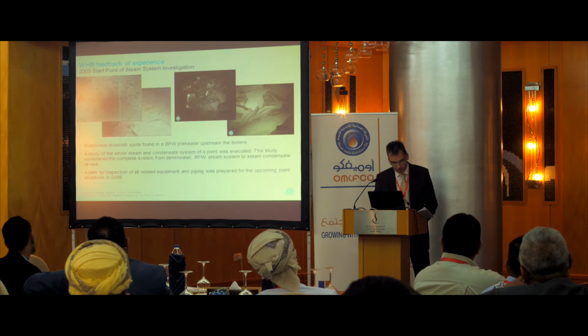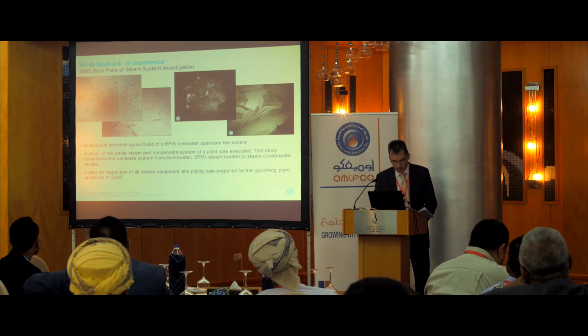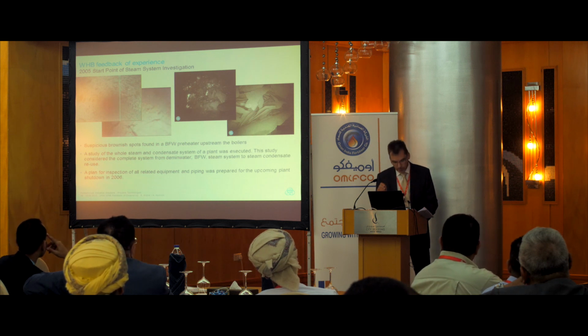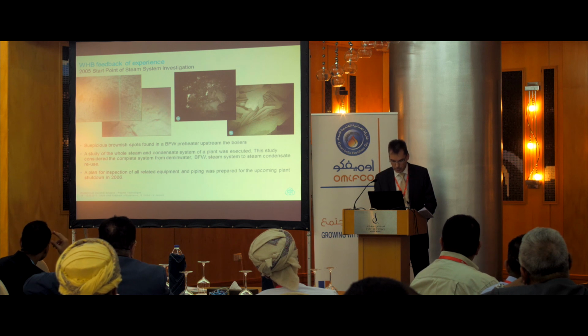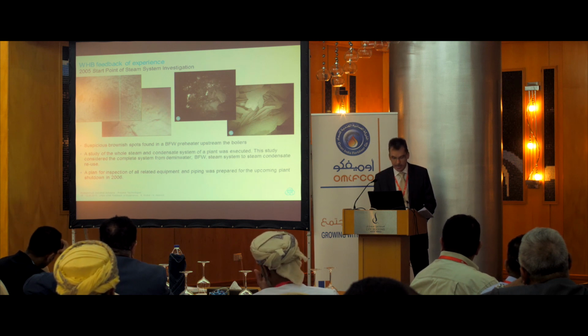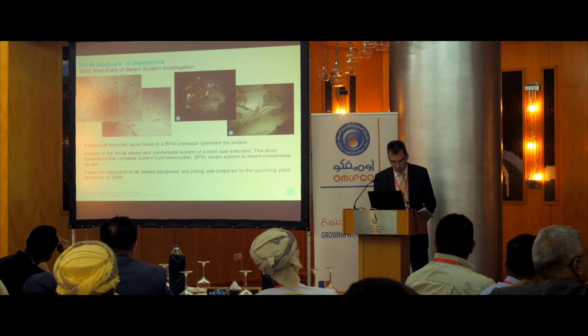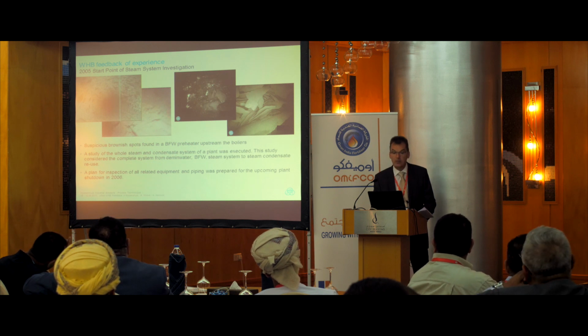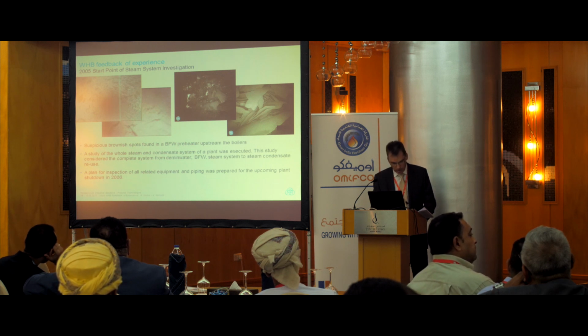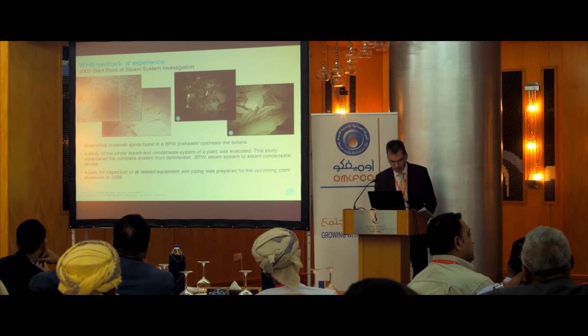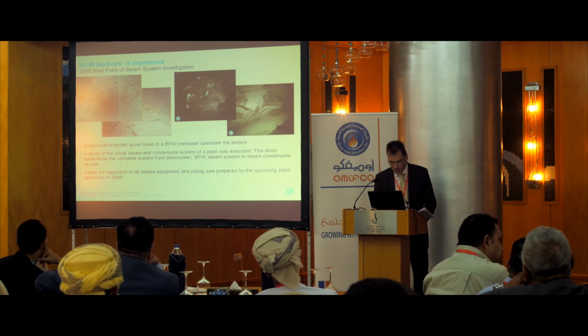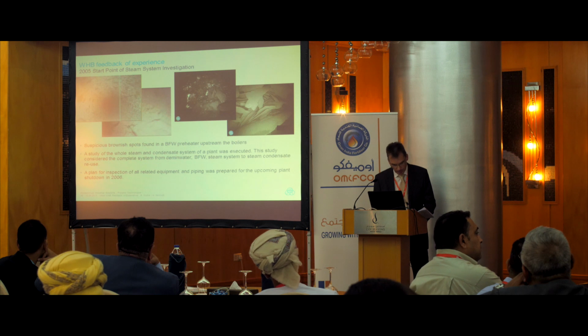In 2005, at one of our plants, a boiler feed water preheater, not a waste heat boiler, failed due to tube vibrations. During investigations inside the stainless steel tubes, brownish spots were found, as you can see on the left top side. This is for sure nothing which should be there, especially not inside a stainless steel tube. This was an indication that something is wrong with the boiler feed water and maybe with the steam system itself.